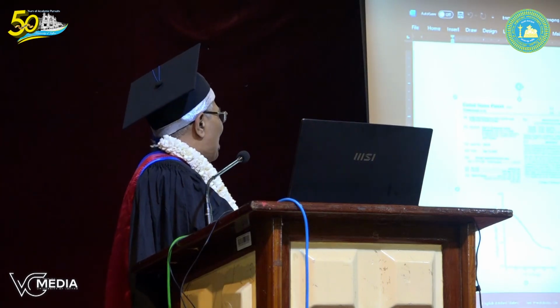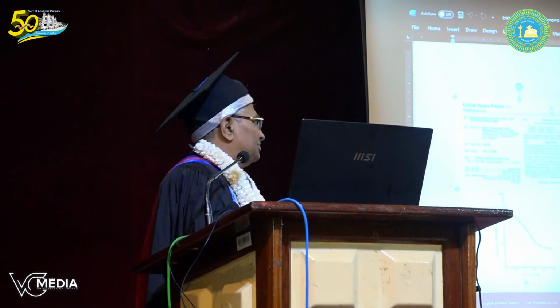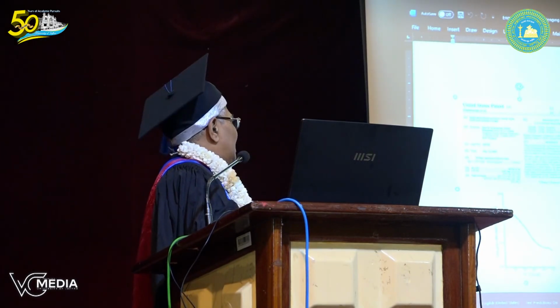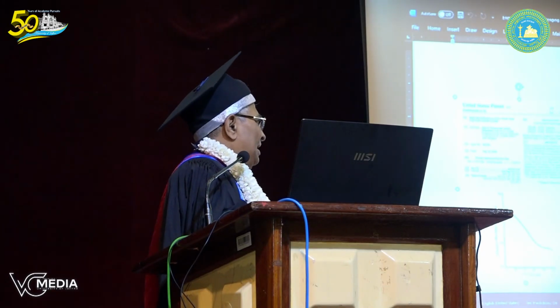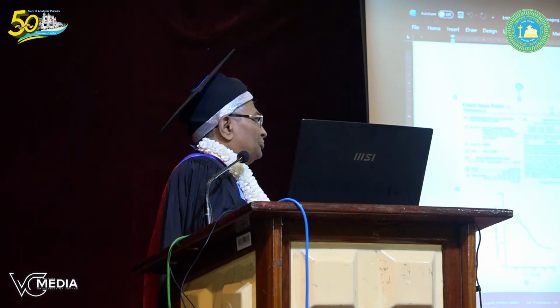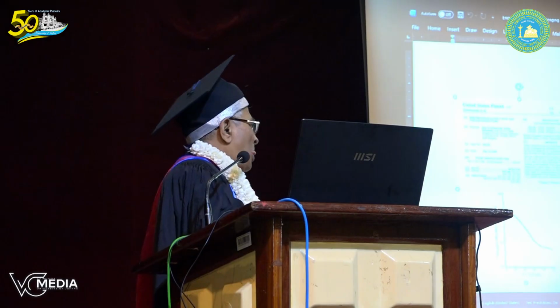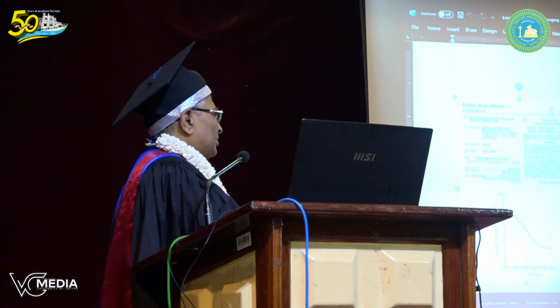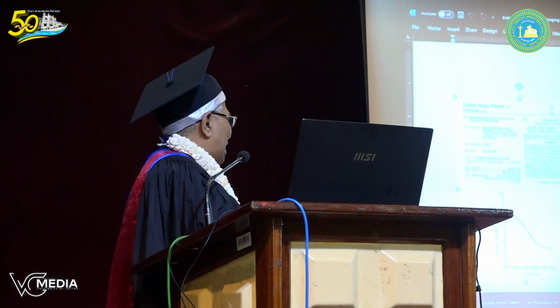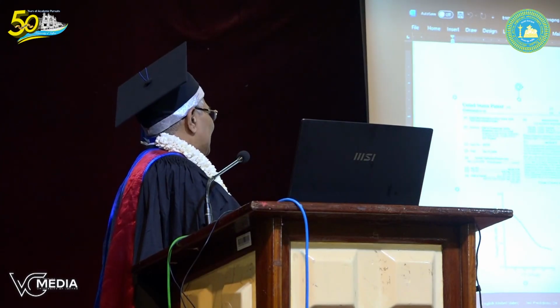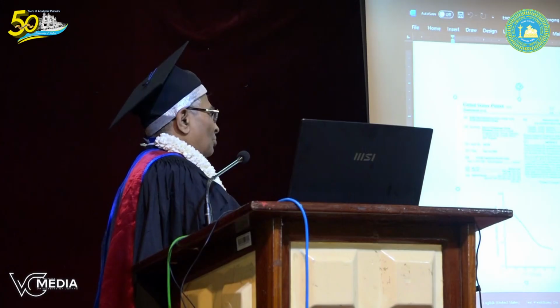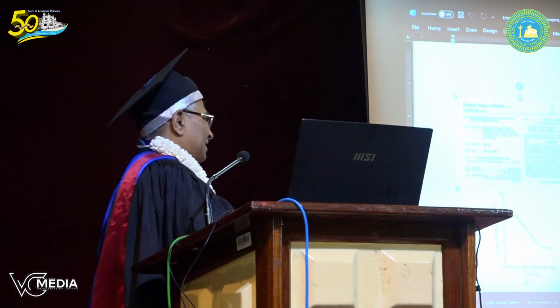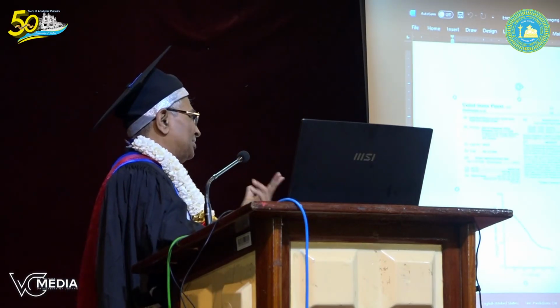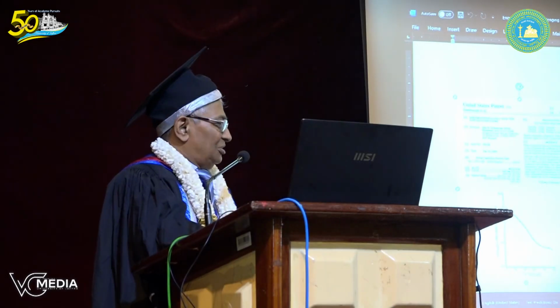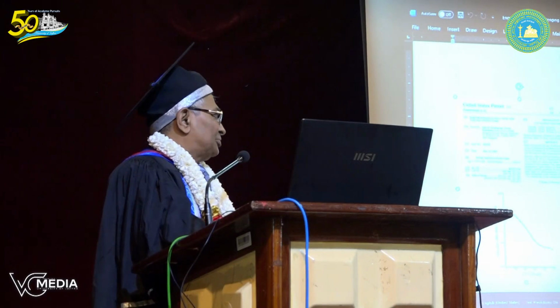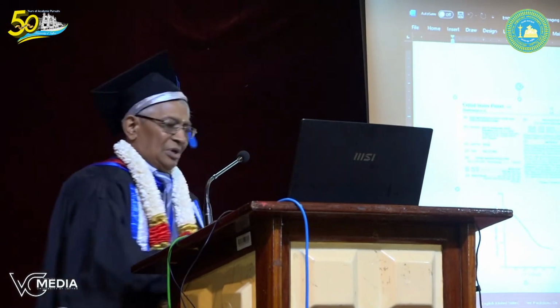And when it is 0.5, the voltage is 4.2. Now, if you charge the battery above 4.2, there will be changes in the crystal structure of the lithium cobalt oxide cathode, and the structure breaks down, and there is oxygen evolution, and so on. The cycle life comes down, and the battery will be damaged. So it's not recommended to charge lithium-ion batteries above 4.2. And so therefore the theoretical energy capacity is reduced to half, because we can't use this whole range. It is reduced to about half the theoretical value, but still it is high enough. It is about 250 watt hours per kilogram, not kilowatt hours, watt hours per kilogram. About 250.